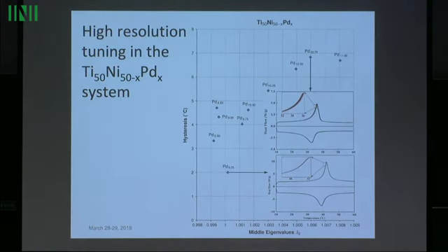This is nickel titanium palladium. As I said, we used to think that was the lambda 2 equals 1 alloy. And then we started changing composition by 1/4% increments, and we got it down to 2 degrees hysteresis here. And the reversibility of the phase transformation, this is a calorimetry graph, also improved quite a bit, just going from here to here. So all these things are incredibly sensitive to composition.